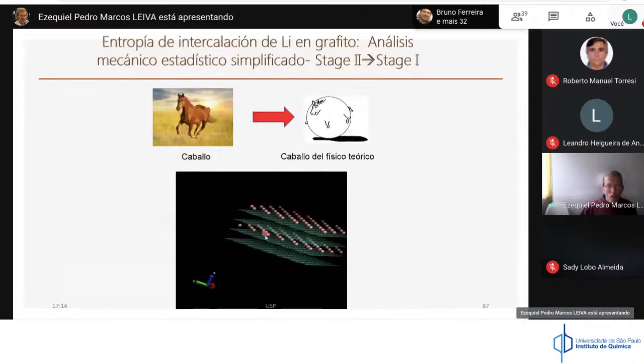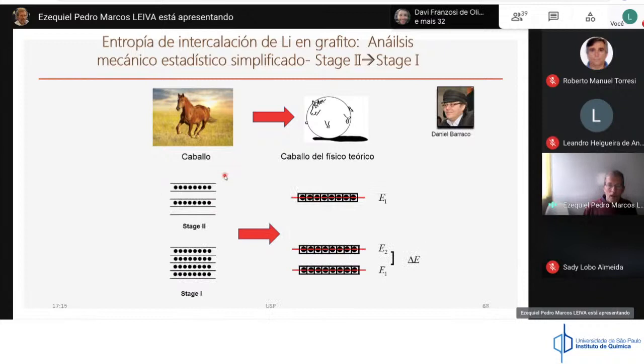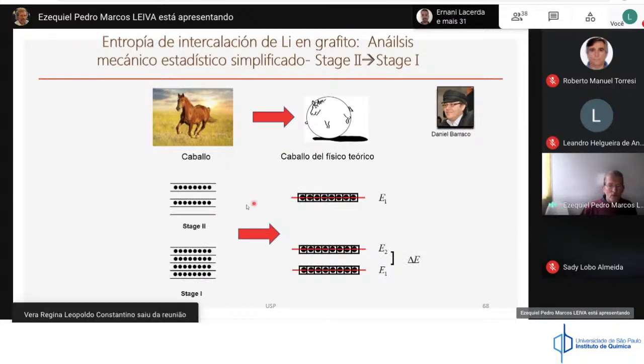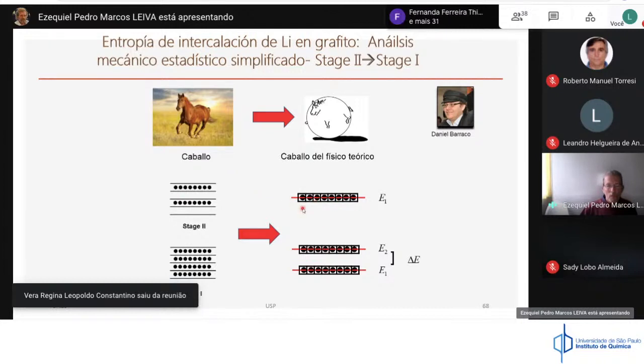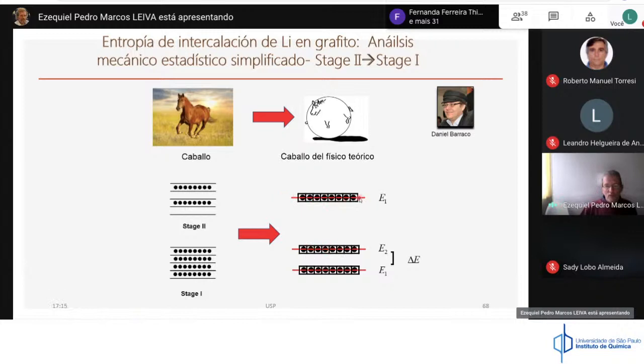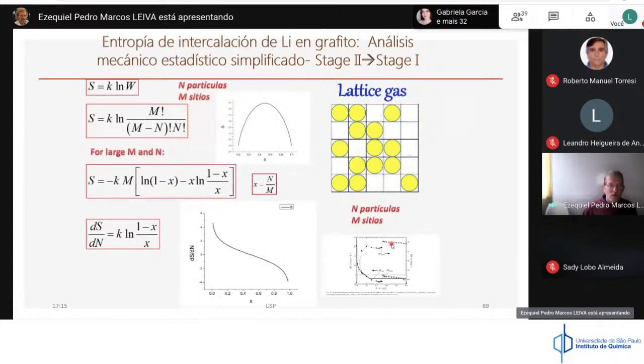Well, it has to do with the fact that when you finish filling an ordered structure and you start to fill a disordered structure, you get a step in the partial molar entropy. We investigated this more, but I will not stop on this. The same thing we did with simulation, you can do with a simple model. Instead of having one energy state, you have 2 energy states. And from this model, you can calculate the properties from statistical mechanics.